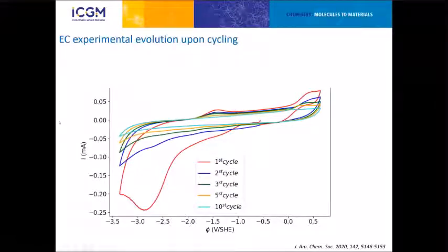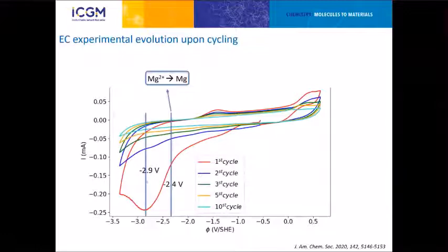In the case of ethylene carbonate, what we observe is, if I set over there the magnesium 2+ reduction process, at the potential where the solvent ethylene carbonate starts to get reduced, we see a decrease in the intensity that is probably linked with the formation of the polymer that starts to form and passivate the whole electrode, decreasing the intensity quickly to very low values.